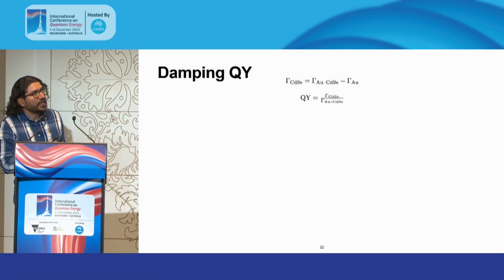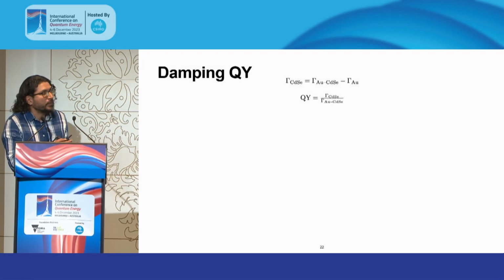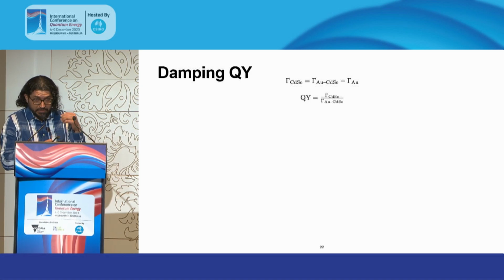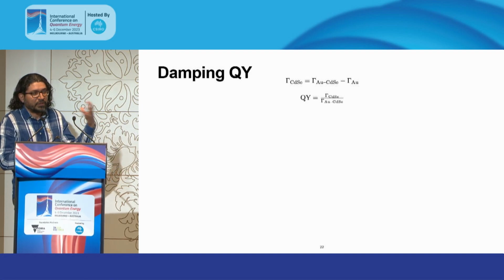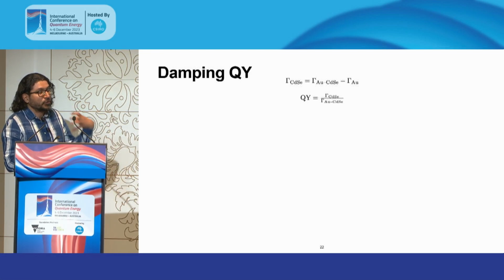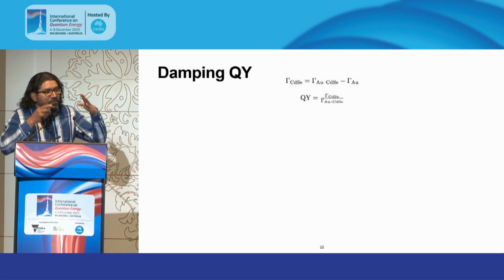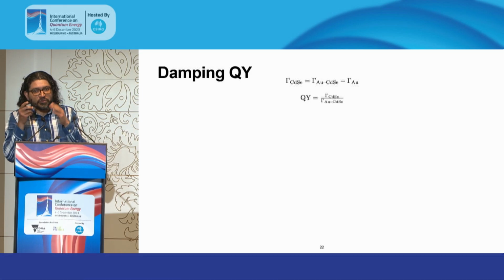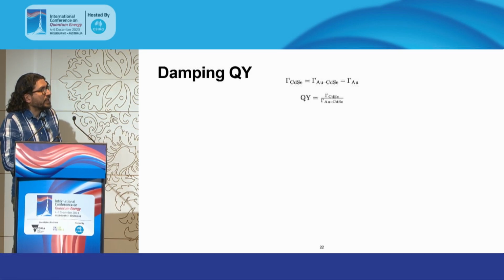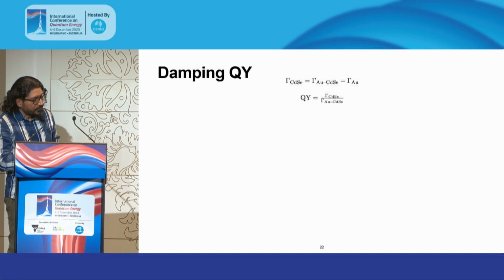To quantify the efficiency of the conversion of photons to electrons, or photons to potentially chemical reactions, we came up with a quantity that we called the damping quantum yield. At the time of submission, our reviewers were extremely critical of us using this word, and we relabeled it as quantum efficiency because we are not really quantifying the number of electrons versus the number of photons. But anyway, this is related to the increase in the line width that we measured with the quantum dots relative to the line width of the plasmon band with just the metal particles.